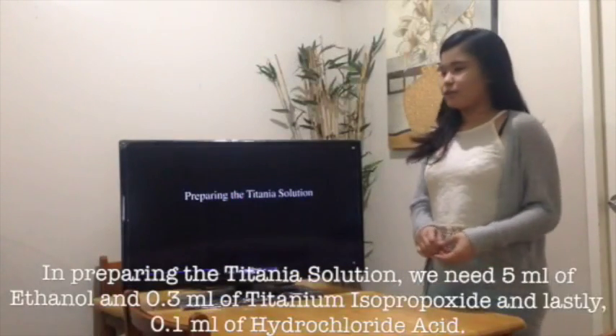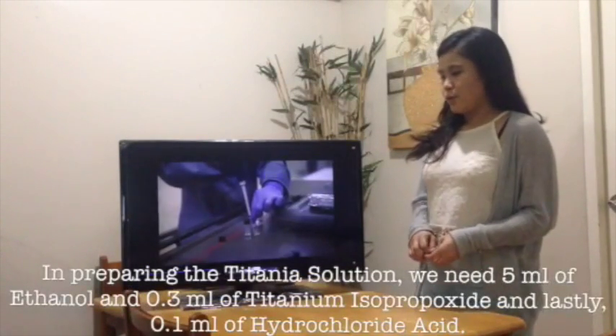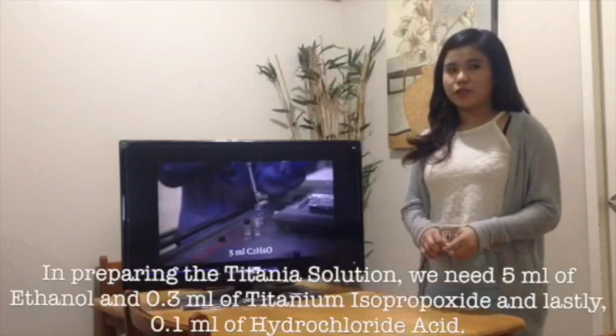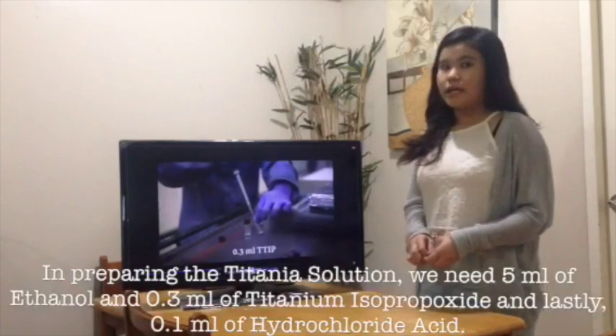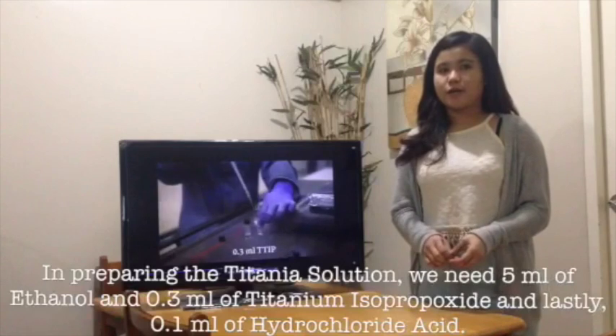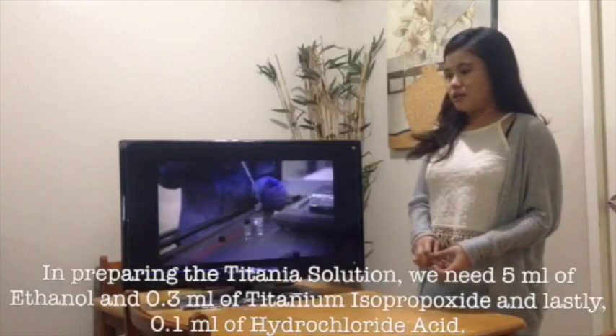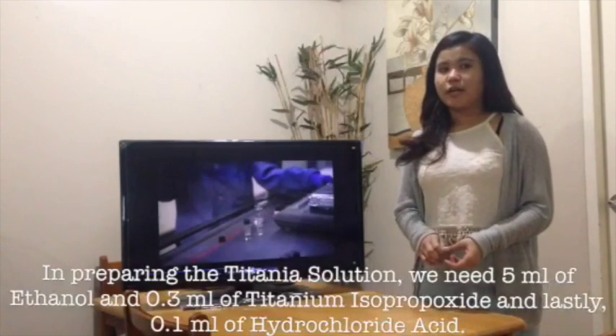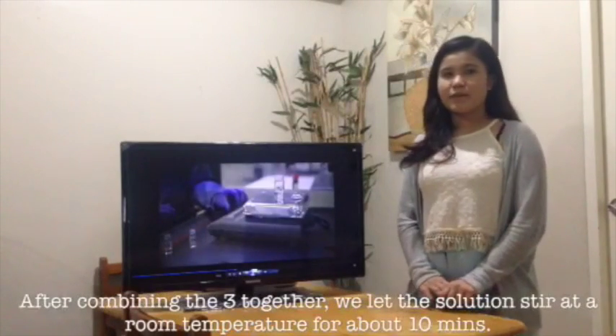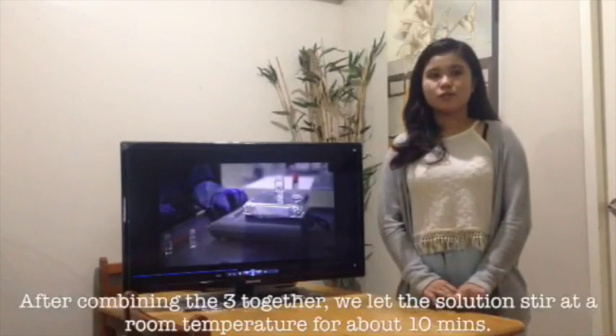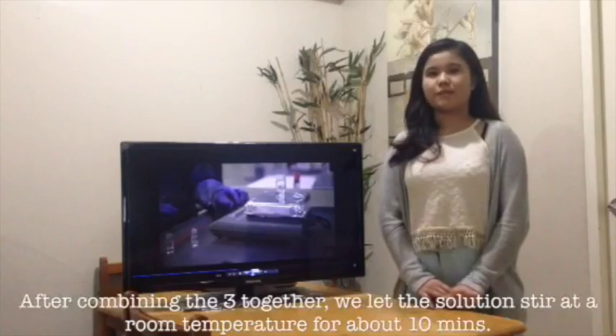In preparing the titania solution, we need 5 milliliters of ethanol and 0.3 milliliters of titanium isopropoxide, and lastly, 0.1 milliliters of hydrochloric acid. After combining the three together, we'll let the solution stir at room temperature for about 10 minutes.